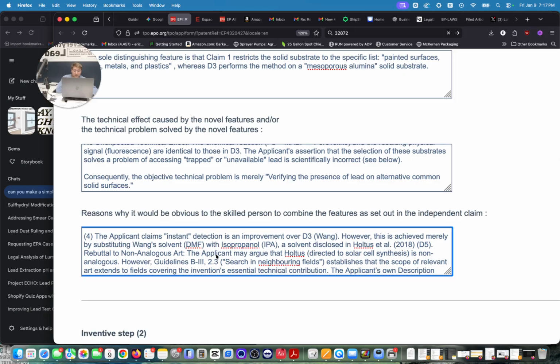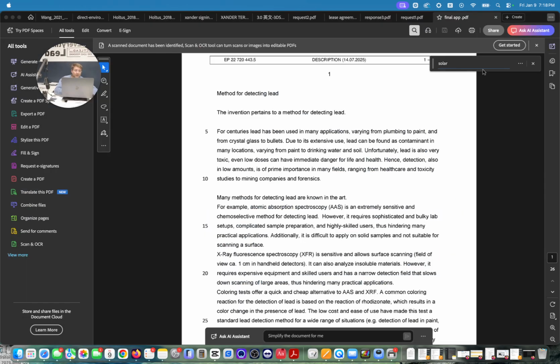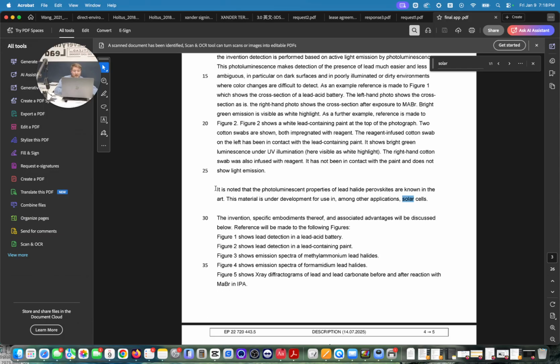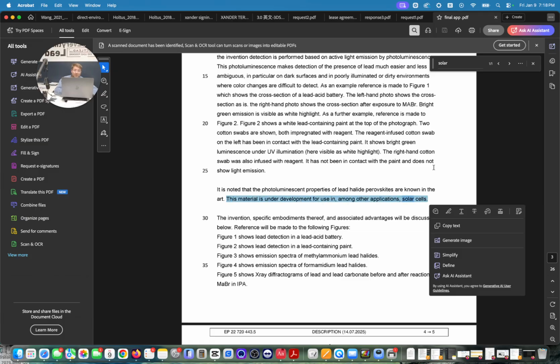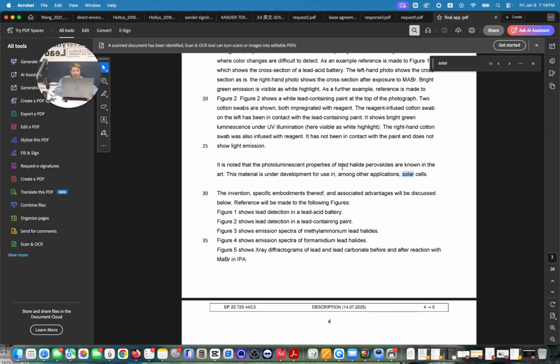But you don't have to, because luckily, Holtus et al. clearly provided the instructions to make the reagent. And that's the same liquid that I use in fluorospec. And the applicant may argue, well, that's a totally different field of endeavor. That's synthesizing solar cell materials, but the application clearly points that it is noted that the photoluminescent properties of lead halide perovskites are known in the art. This material is under development for use, among other applications, solar cells. And they know that because they themselves worked with it, making solar cells. Couldn't help but drop that in there.